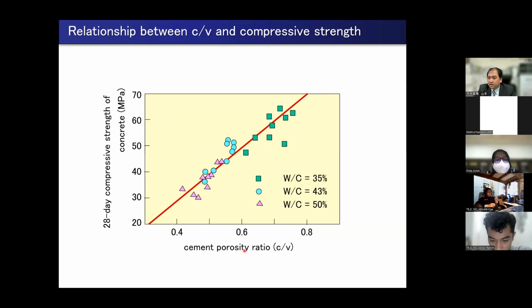And here, this diagram shows the relationship with C by V. V means void. Cement porosity ratio. If the void of cement is smaller, then the strength of concrete will increase. To make the void smaller, we have to choose a smaller water to cement ratio. Here, this green plot indicates 35% water to cement ratio, and this pink triangle plot indicates 50% water to cement ratio. To reduce the void inside the concrete, we have to choose a smaller water to cement ratio. Then the strength of concrete becomes higher.